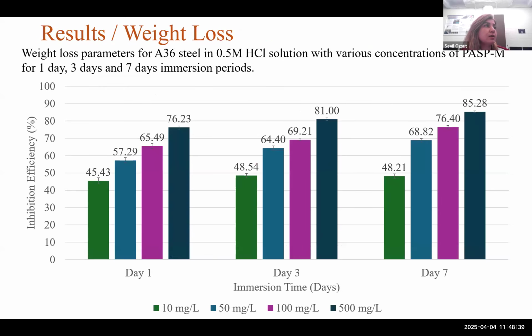Here are the results for the weight loss. This is the weight loss analysis for methionine functionalized polyaspartic acid for three different duration times. All these bars show the different concentrations. As you can see, for all duration times, we get an increasing trend as the concentration increases. The highest concentration was 500 milligrams per liter.